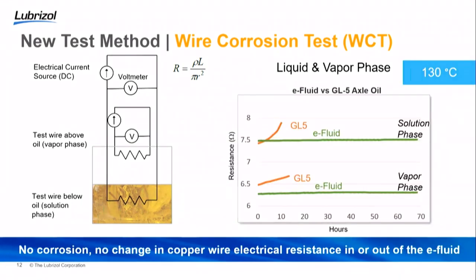So you can see in the graph the resistance on the left with time. And if you have no corrosion, there would be no change in that copper wire electrical resistance in the fluid or out in the vapor phase. And that's demonstrated by the green line, the e-fluid line, over a number of hours. In fact, we've run some up to 1,000 hours with no change in resistance of that wire, so absolutely no corrosion in the system. In contrast to a GL5 fluid, which is a typical sulfur-heavy loaded fluid, you can see that after quite a short time in the solution phase and the vapor phase, that wire actually corroded to such an extent that it broke. So that's where you get the break at 10, 15 hours. So it's really a new test that can look more closely at what's happening with corrosion.